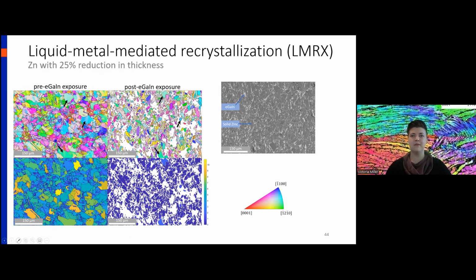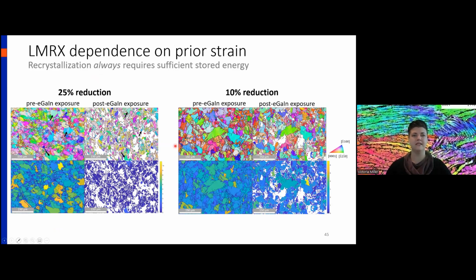Note that this same effect is present, but only weakly present when you have a 10% reduction in thickness versus a 25% reduction in thickness. At 10%, you don't have the critical strain to initiate recrystallization. So this is very interesting. This is a relatively new recrystallization mechanism.